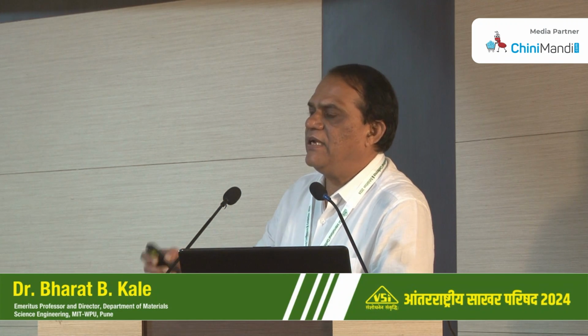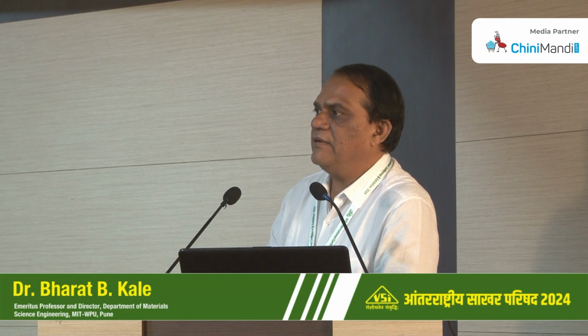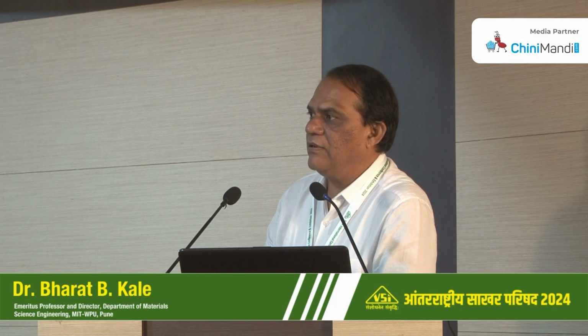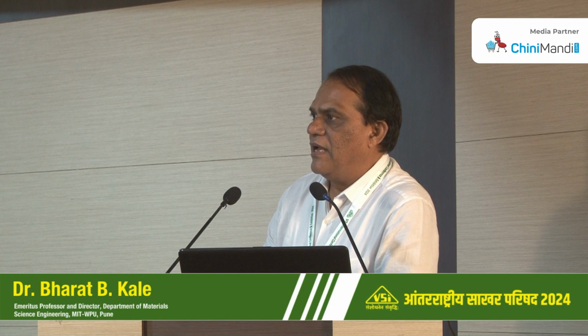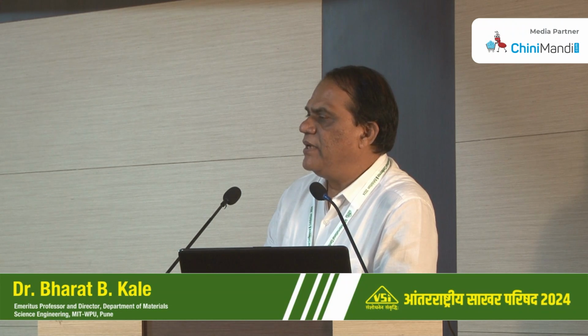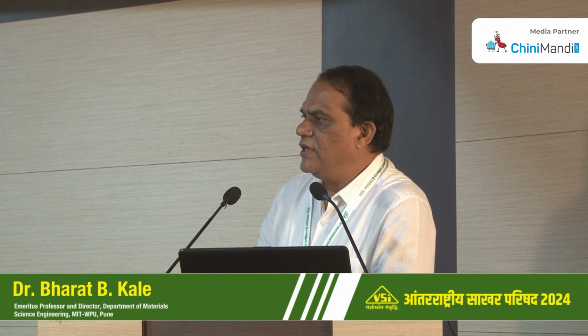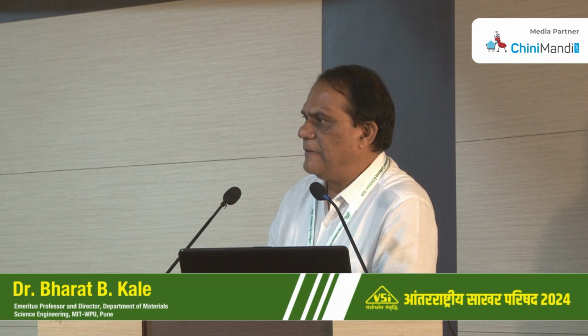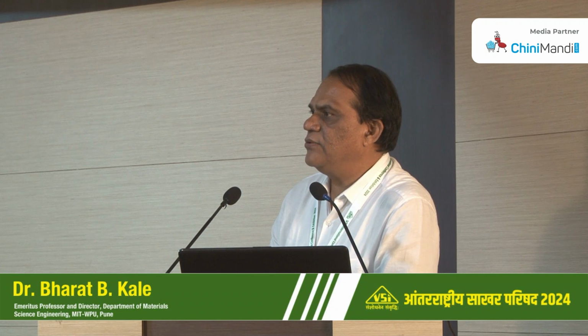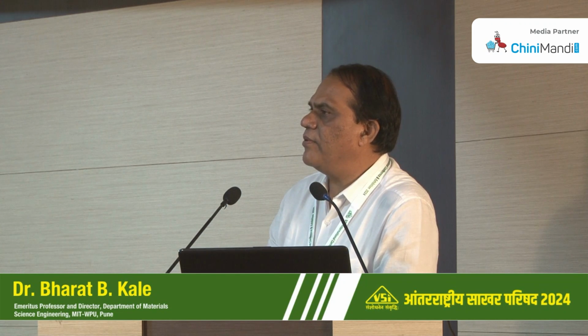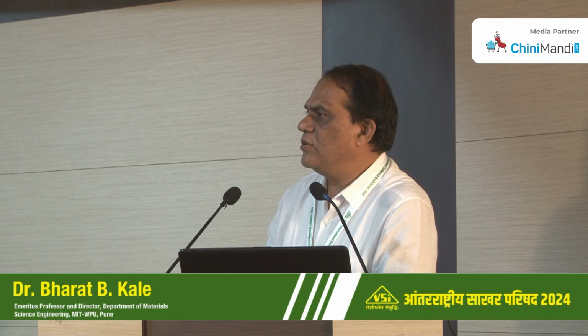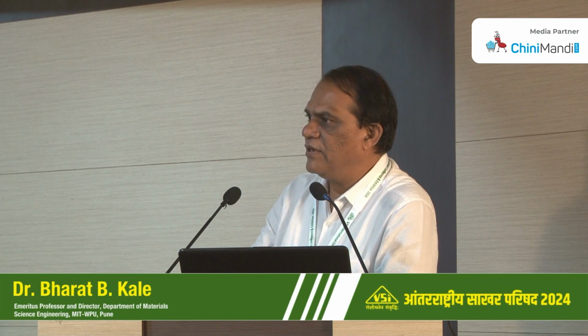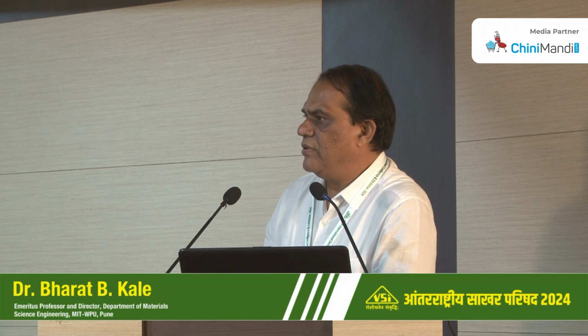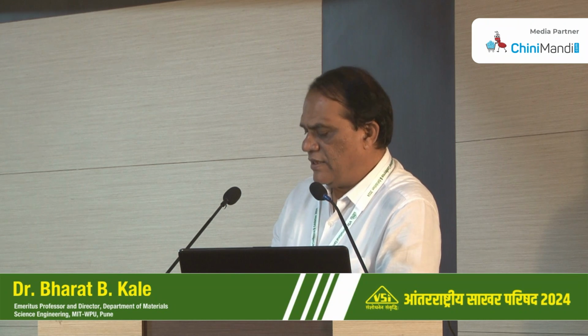So that's why we thought that we can have a very commercial way to make this glass, and we did it. This is a big 5 kg block we made, and 4 kg for silicate glasses, and repeatedly we got good results. You can see similar crystal growth inside the glass, and similar band gap extension we observe in these glasses.